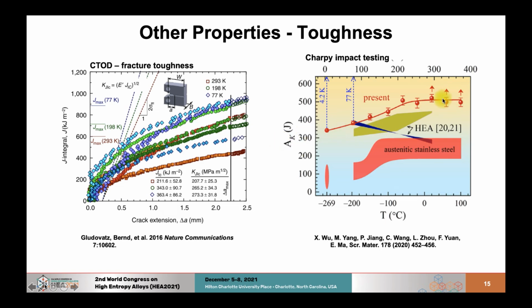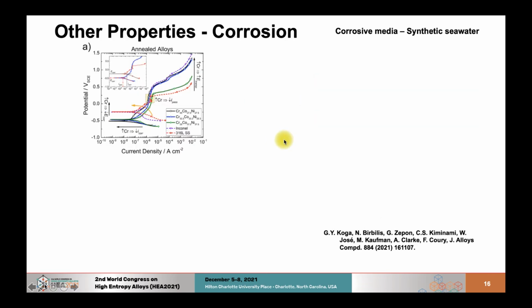the absorbed energy goes down as temperature goes down. So they do a nice discussion of this. The trend is somewhat inverse, but nonetheless, the absorbed energy is very high, typically larger than what you see for conventional materials and also other HEAs. So the toughness of these alloys is very, very large.